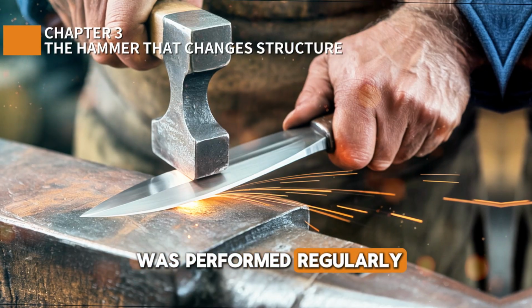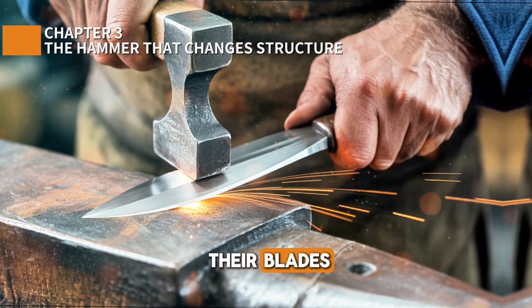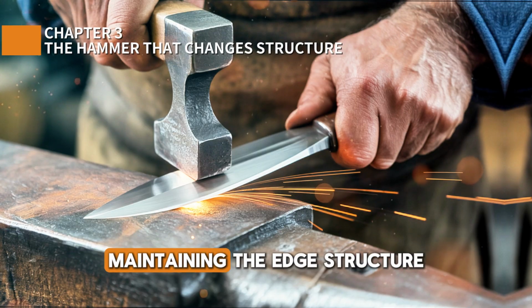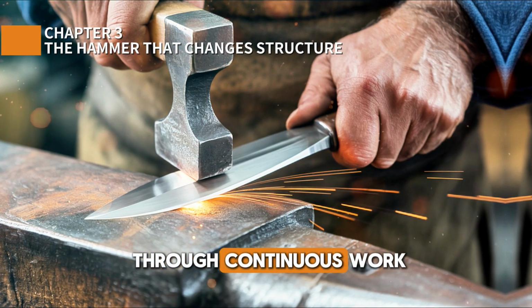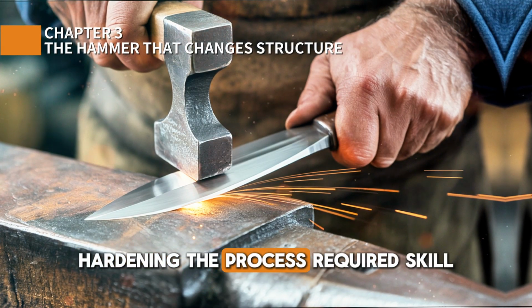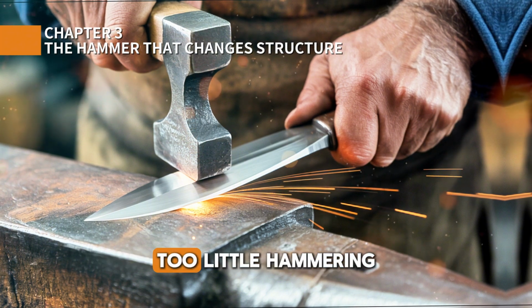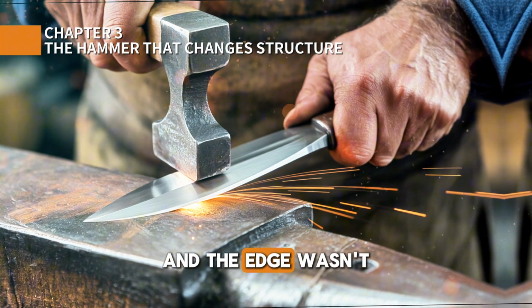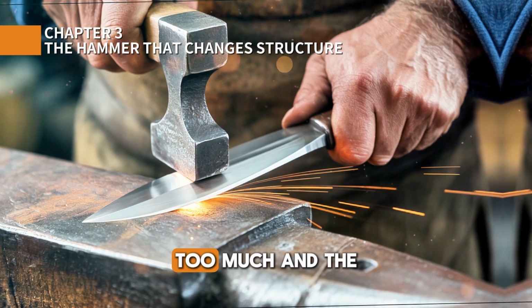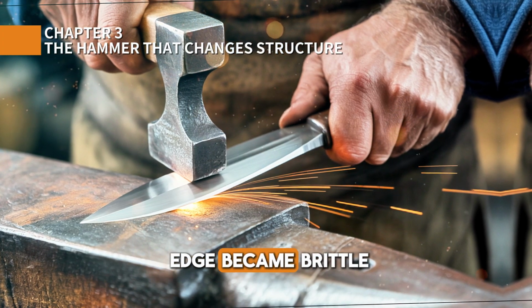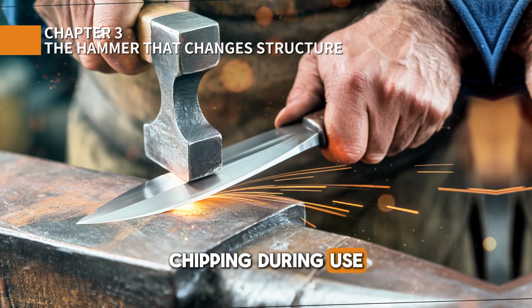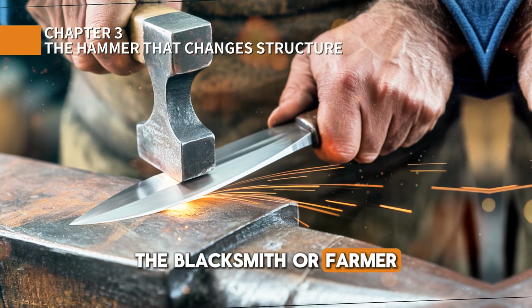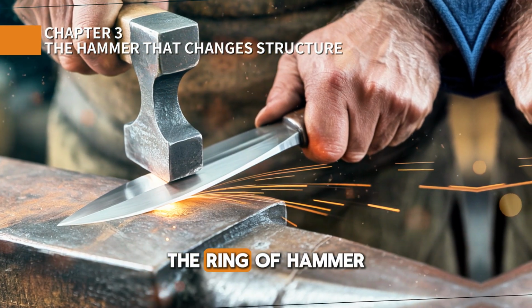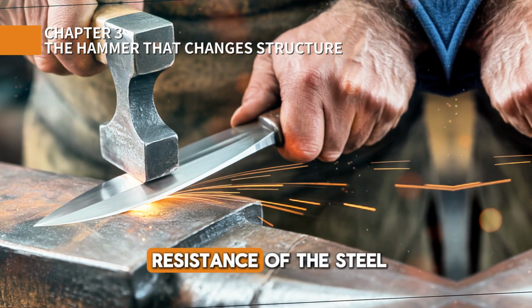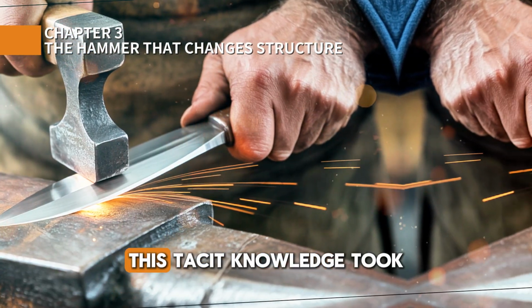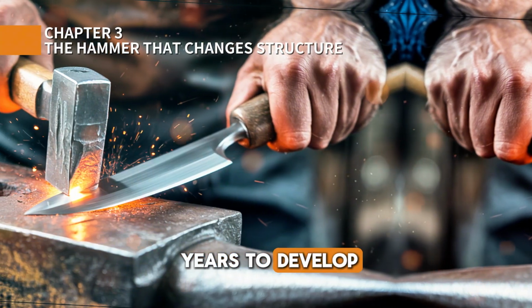It was performed regularly. Scythe users would peen their blades every few hours of cutting, maintaining the edge structure through continuous work hardening. The process required skill. Too little hammering, and the edge wasn't adequately hardened. Too much, and the edge became brittle, chipping during use. The blacksmith or farmer had to judge the correct amount by sound, the ring of hammer on steel, and by feel, the resistance of the steel to deformation. This tacit knowledge took years to develop.